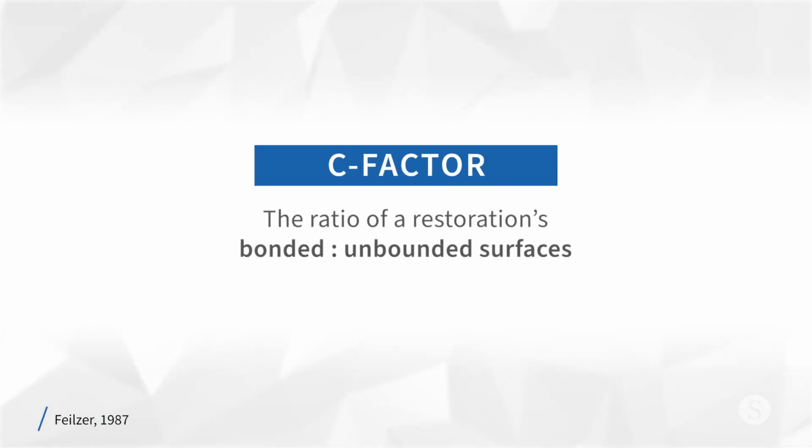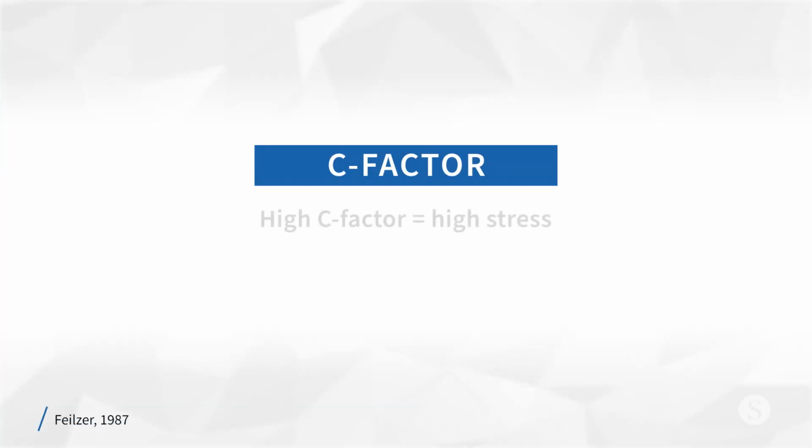C factor is the ratio of a restoration's bonded to unbonded surfaces. The bonded surfaces being the surfaces of the composite that are actually touching the tooth, the unbonded surfaces being the surfaces that are free to the air. High C factor, in other words a restoration with a large number of bonded surfaces, gives high stress.